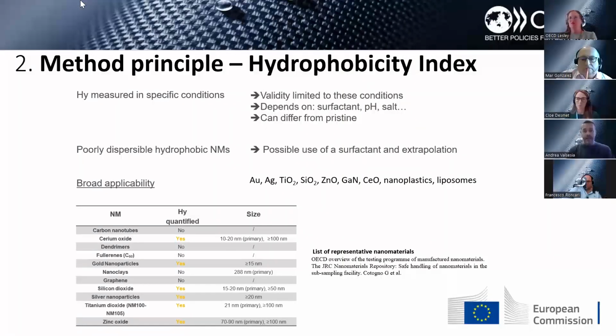And then my colleague Chloé a bit later on will show that we can disperse this material using a surfactant at different concentrations, and we can extrapolate the value of the hydrophobicity index when the concentration of the surfactant is 0. This also enables us to measure the hydrophobicity index for really hydrophobic nanomaterials.